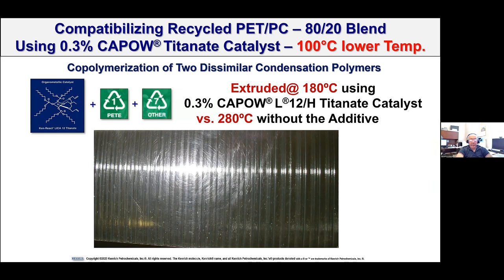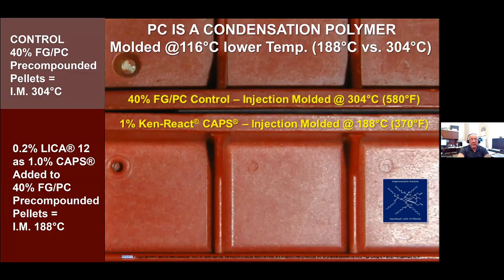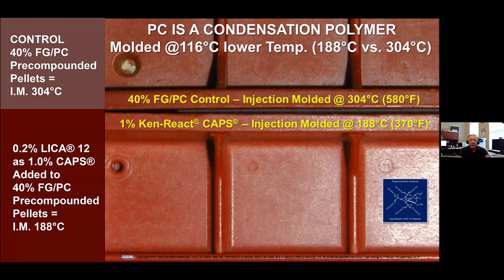We were able to combine lots of different products at 100 degrees centigrade, lower temperature, between two condensation polymers. One customer we've had for almost three decades was injection molding knife sharpeners — the base was 40% fiberglass-filled polycarbonate. They were having problems with the stability of the weld-line flow and the material itself. They put in 1% of a pellet master batch containing 20% active titanate. With that 1% addition they got the product to show smoothness, brightness of colors, and they were able to do it at 116 degrees lower temperature.